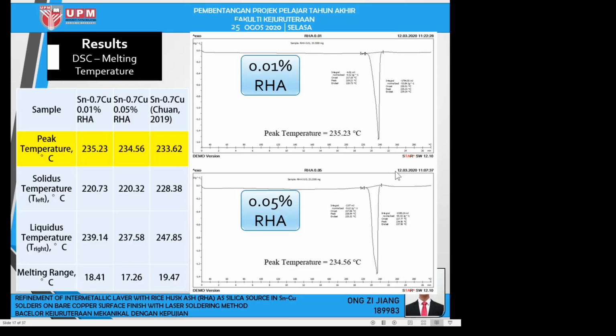Here comes the results and discussion part. Firstly, the DSC result shows that the 0.01% RHA solder has a peak temperature of 235.23 degrees Celsius, and the 0.05% RHA has a peak temperature of 234.56 degrees Celsius. Compared to the plain tin 0.7% copper done by Chuan in 2019, whose peak temperature is 233.62 degrees Celsius, this means that the addition of the RHA causes the melting temperature to rise slightly.